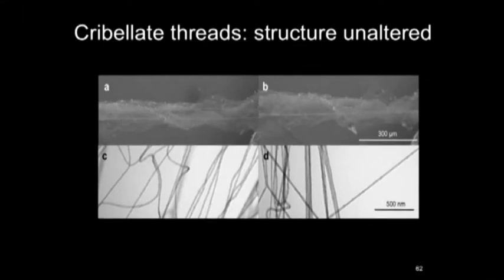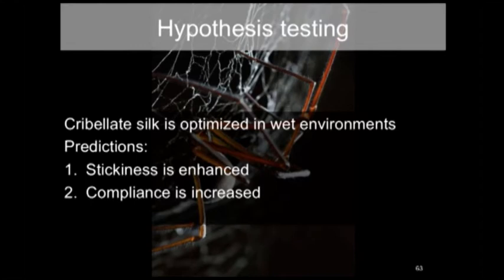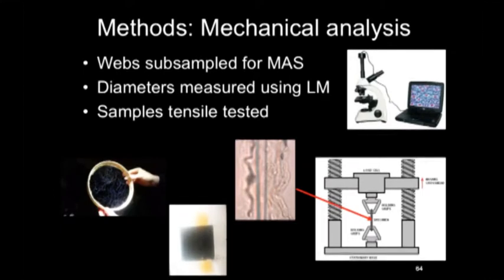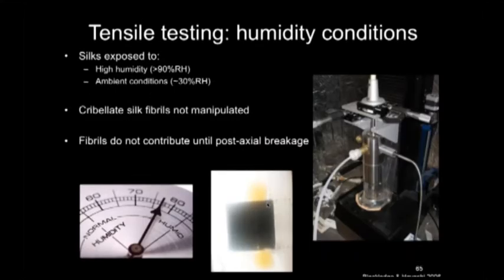So we wanted to test if the cribellate silk is optimized for wet environments by looking to see if stickiness or adhesive work increases and if compliance of the underlying fibers increases. So once again, back to the caves, collecting the cribellate fibers, and you can see the bluish hue there. We're collecting those pieces and then putting them onto the same machines and the methods similarly described as before, and running tensile tests, and we expose them to wet and dry conditions, similar to how we talked about before. However, one thing is that the cribellate silk fibrils were not manipulated, but they do not contribute until those axial fibers break. So their contribution is very low, so we can easily identify the actual performance of the underlying fiber.